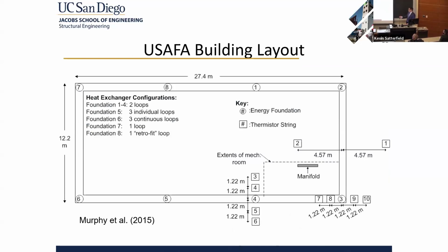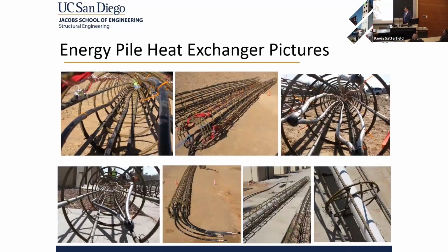2 of the piles have instrumentation off to the sides, and piles 4, 3, and 1 have strain gauges throughout their depth. These were 24-inch diameter piles, so they're relatively narrow, but you can see the pipes on the inside of the reinforcement cage. One of them we were looking at as a retrofit, where you would maybe core down through your pile and install a vertical heat exchanger into the middle. So to replicate that, we just had a pipe in the center of the pile that we inserted the tube in later. After we had these pipes attached, we pressurized them with water and had a valve at the top, and we could use that as a way to detect if there was any leaks during the construction process.